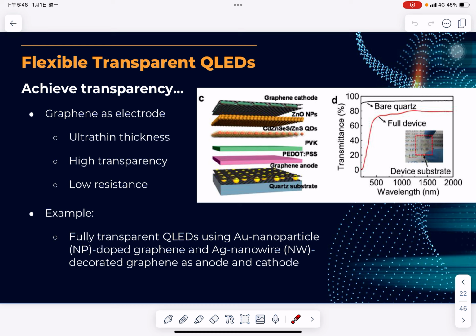Graphene with gold nanoparticles doped and silver nanowire decorated variations forms fully transparent QLEDs, incorporating gold nanoparticles and silver nanowires to adjust energy levels while maintaining transparency and low resistance. The structure is like this.